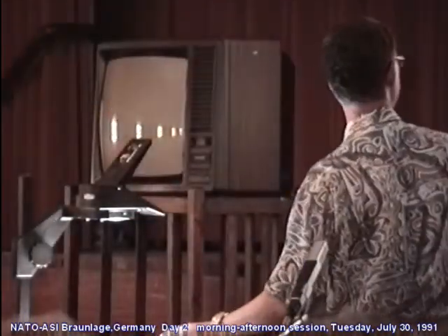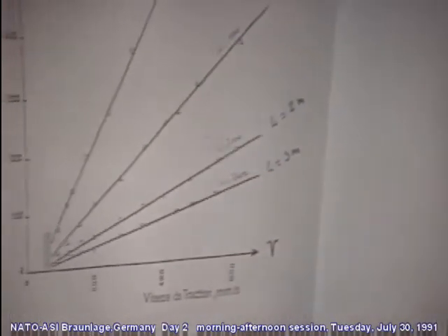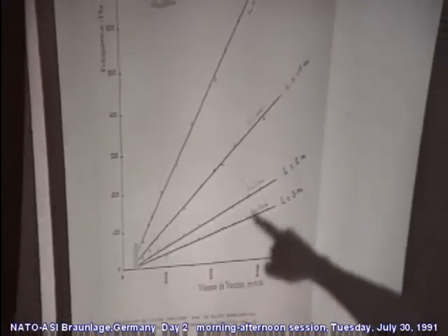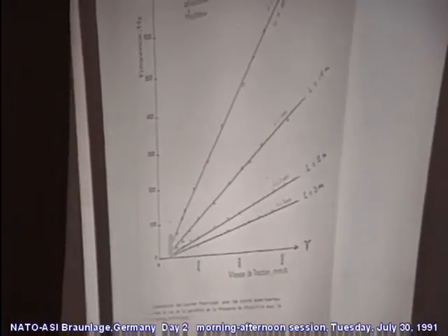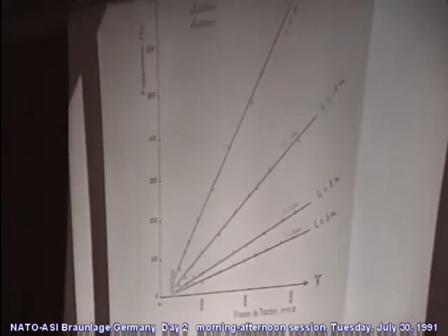The comparison with the experimental result is very correct. Because the frequency goes from 100 Hz to 700 Hz as a function of the imposed velocity capital V. Here is the experimental point, and here is the expression calculated without any adjustable parameter.